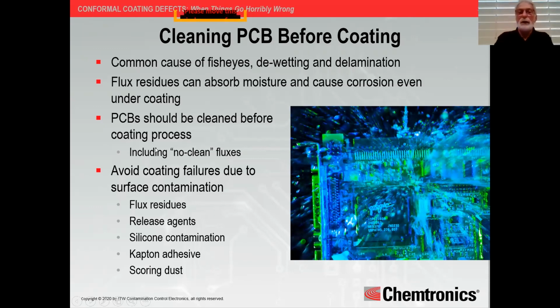There we go. Okay. Cleaning your PCB before coating. Well, here's the deal. Coating loves clean. The cleaner it is, the better chance you're going to have of good bonding energy, good adhesion, good coverage, and less potential defects. Non-cleaning or improper cleaning or lack of cleaning are common causes of fish eyes, dewetting, delamination. Flux residues, if they're not clean, can absorb moisture and cause corrosion even under the coating.